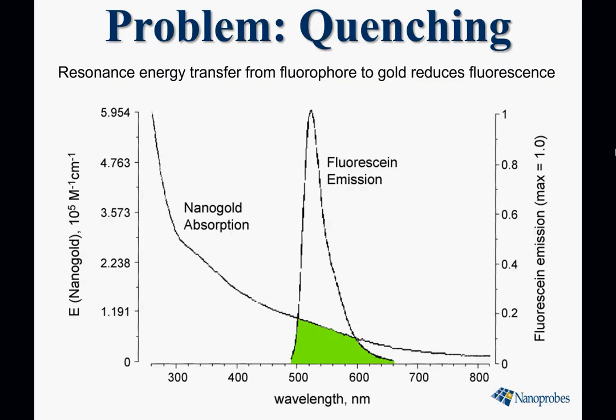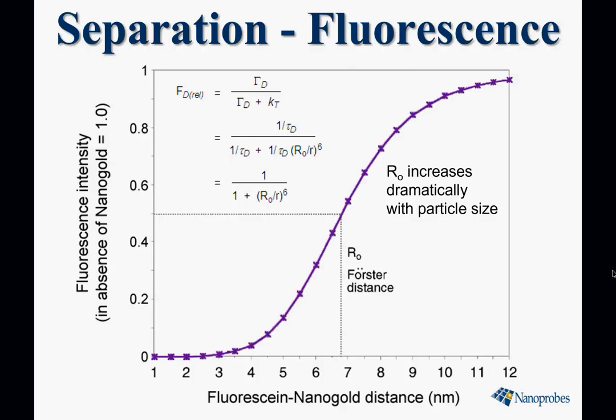Here's the problem with fluorescence quenching, which I referred to earlier. Gold nanoparticles are actually pretty good absorbers of fluorescence emissions by resonance energy transfer, and that diminishes the fluorescence. And here's the overlay of the fluorescence emission of fluorescein with the absorption of our 1.4 nanometer Nanogold. Nanogold doesn't have the highest absorption in the region where many fluorophores emit. So the overlap cross-section is not tremendously high with Nanogold. It is, though, much higher with some other fluorophores.